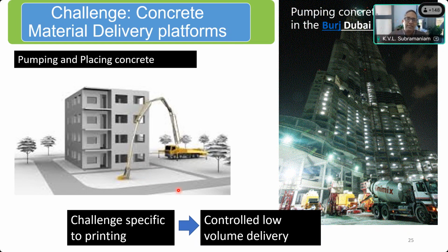But the challenge that is very specific to printing is this controlled low volume delivery. When you're talking about pumping large volumes of concrete, I have technology readily available. But what is required for printing is I need precise control on the volume. I should be able to adjust the volume being delivered very precisely, and the volume I'm delivering at any given time is very small. So here I have to go from something which is a monster, which is basically what has been used for delivering on Burj Khalifa, and start talking about a minutely controlled system where I'm able to control it very precisely. So this is the first challenge that is faced by the concrete printing technologists.